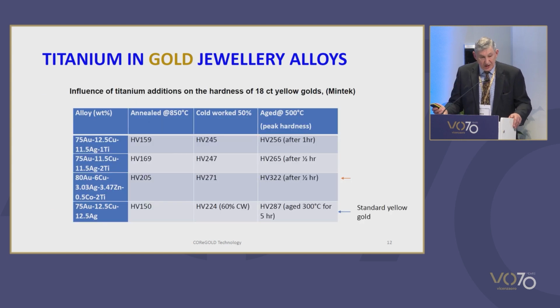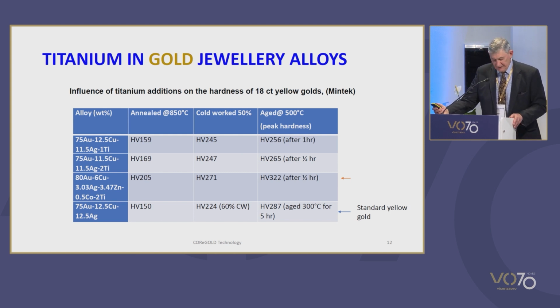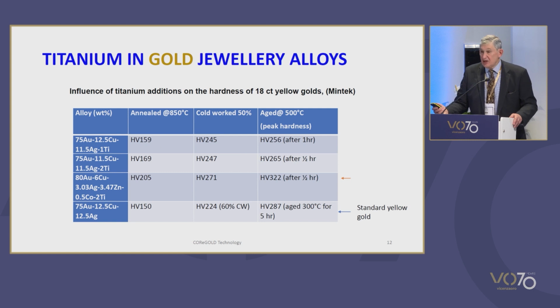The table gives some results in terms of hardness for additions of titanium compared to standard 18-carat yellow. The target hardness of 300 Vickers was only reached with a 2% titanium plus a 0.5% cobalt addition. However, the alloys were a pale yellow colour and the formability of the alloys was compromised. So in their study, the use of titanium was not pursued further.